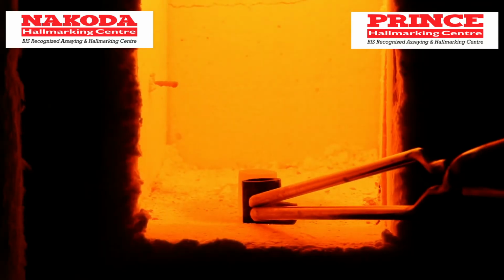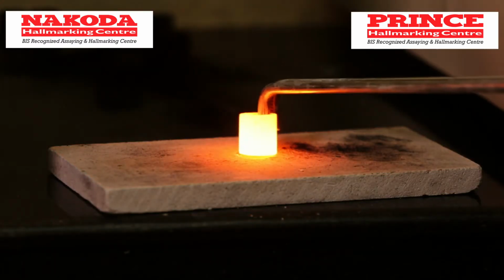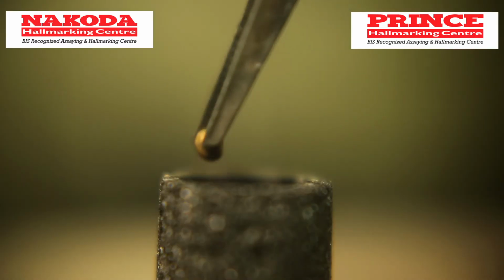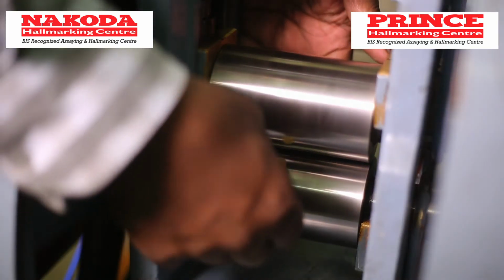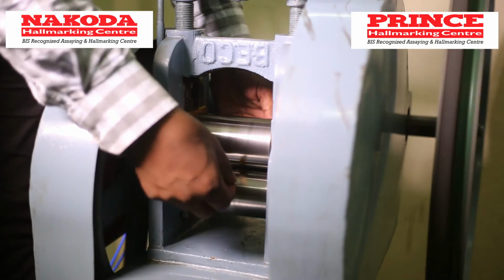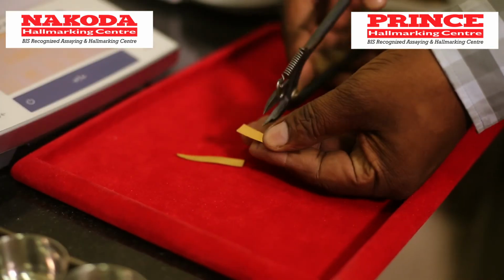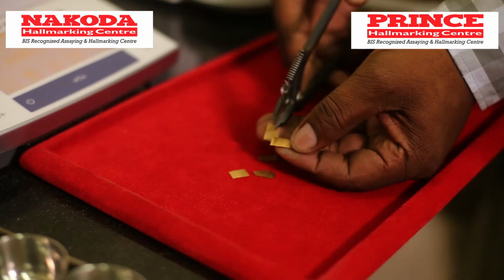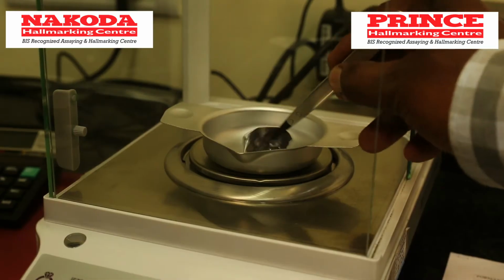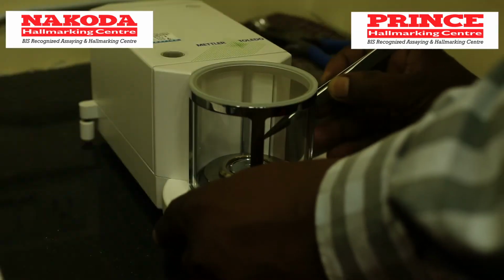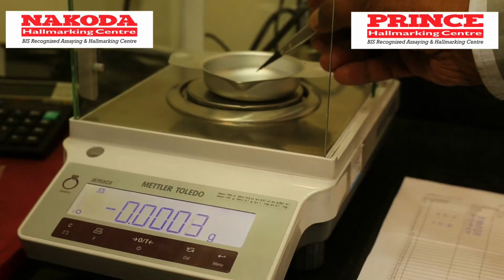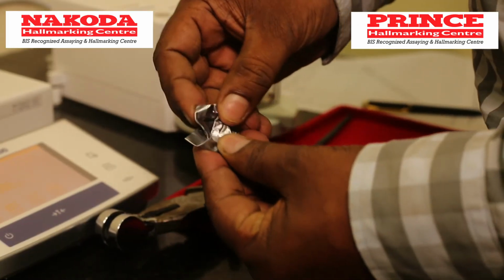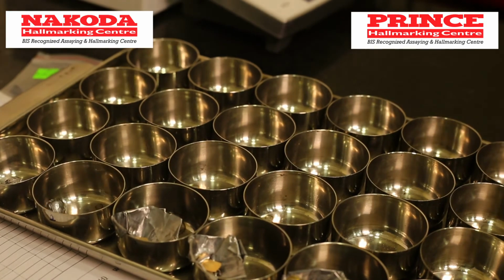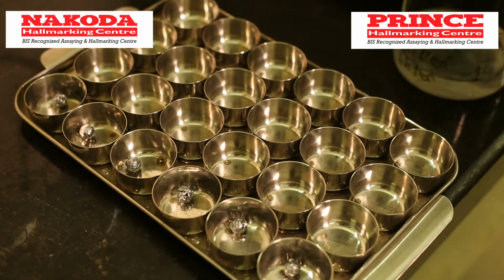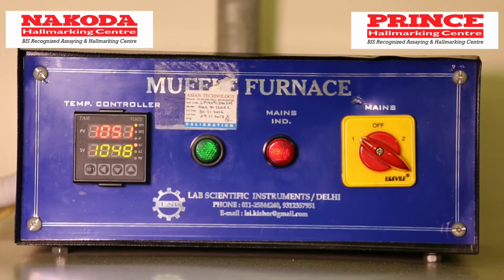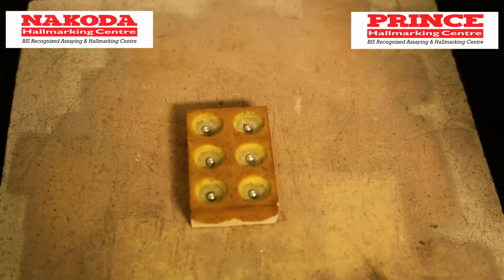Each of these samples is melted in graphite crucible separately so that it becomes homogeneous piece. After that, these samples are flattened, then rolled into small strips, then cut so as to get 2 pieces out of each sample for testing in duplicate. These are then weighed, and then an appropriate amount of silver is added to each. These are then wrapped in lead foil and made into small balls, which are then put into cupellation furnace for cupellation. By this process, all base metals like copper are removed and only gold and silver remain in the sample.